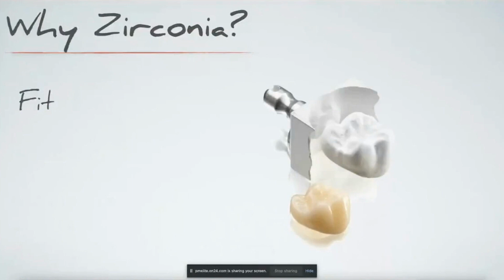Another thing we like with Zirconia is the fit. When I teach classes and talk to doctors, I always hear, Zirconia fits so well, the margins are so great. And there's a couple of reasons why that happens. If you haven't used zirconia in your office or you haven't seen zirconia milled, what you're seeing in this picture to your right is actually zirconia milled and then zirconia sintered. And zirconia is going to shrink roughly 28% or more during the sintering process.